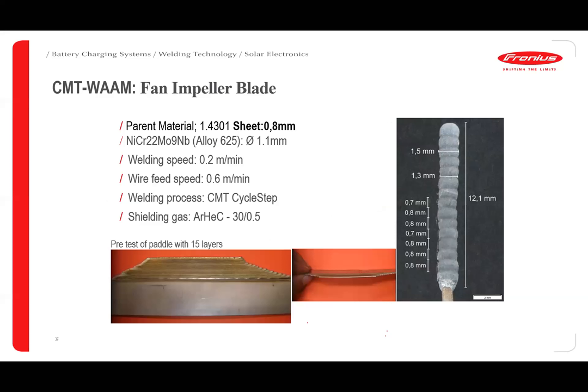Coming to the next experiment of building a small impeller blade, which is of thickness 0.8 mm. You can imagine how thick 0.8 mm is. You can take a few of your A4 sheets and keep them between 2-3 layers, and that will be the thickness of 0.8 mm. In this 0.8 mm also, we have done a deposition of an Inconel alloy. The Inconel is a nickel chrome moly alloy, which we have welded in close to 15 layers. And we were able to achieve these layers almost equivalent to one over another.